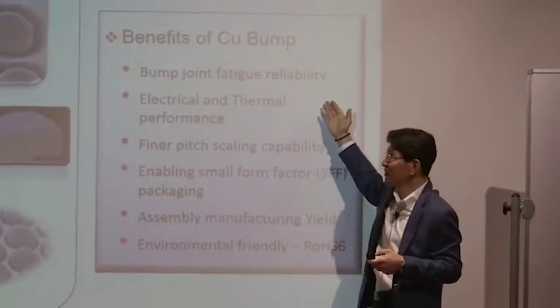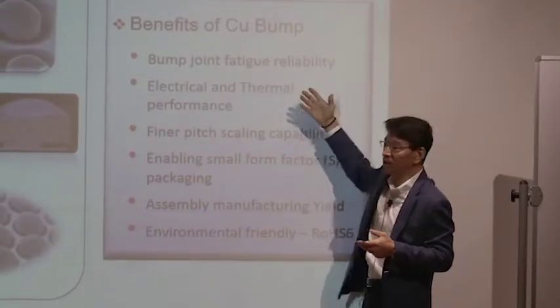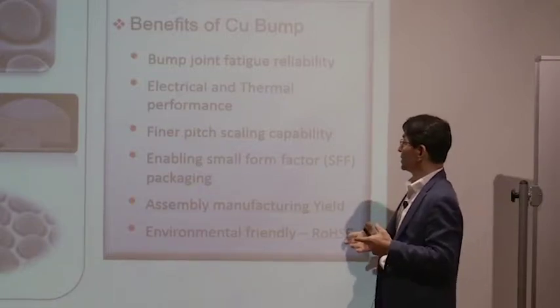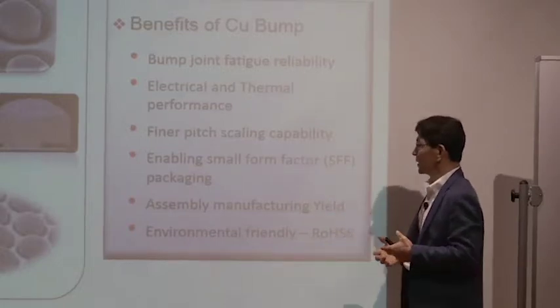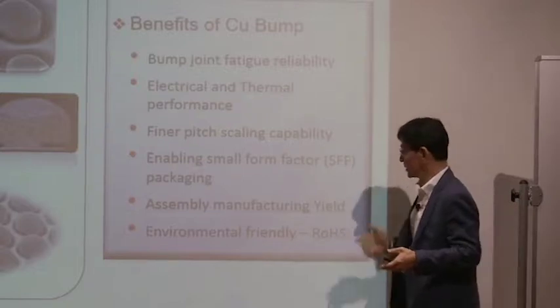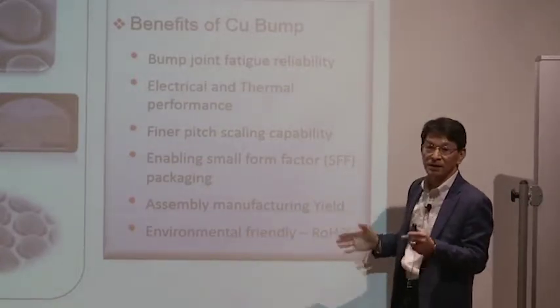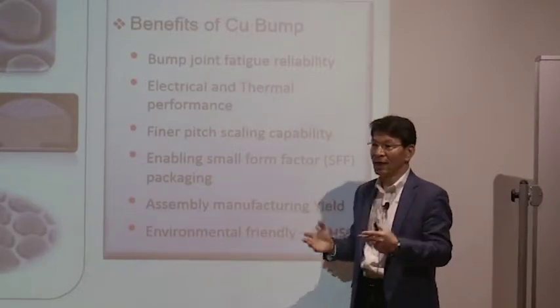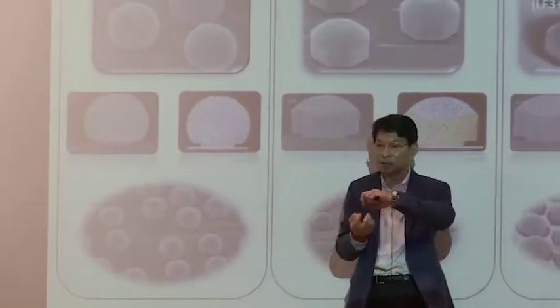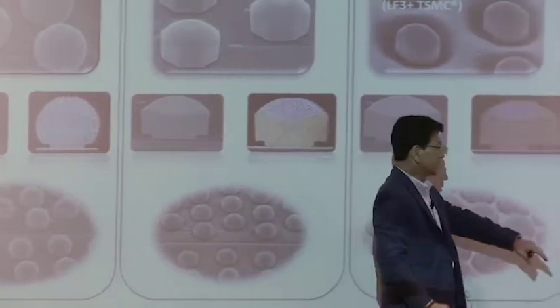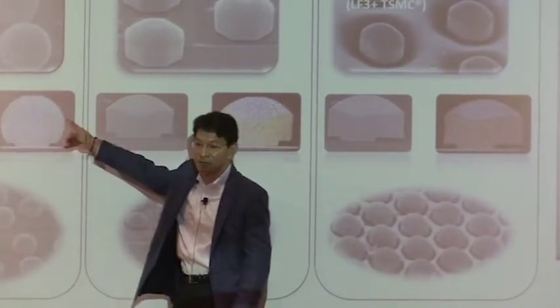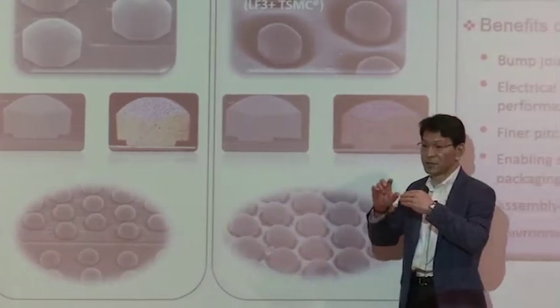So the benefit of this copper compared to solder is more fatigue life, mechanically more durable, and the electrical and thermal properties of copper are much better than solder. And fine pitch scaling, and it also supports small form factor. The manufacturing yield is better. And it also meets RoHS 6. This is an environmental requirement across the entire world, not to use any lead. So old solder bumping has tin lead, the alloy. And then since RoHS 6 agreed not to use lead, we changed the metallurgy from tin lead to tin silver. And it increased the melting temperature about 20 degrees C, but this makes the world beautiful.